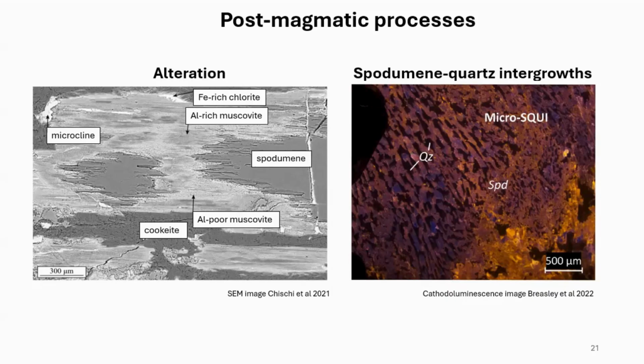It undergoes this calcination. To get the lithium out of solution is another story. That's lithium hydroxide, carbonate, all that stuff. But just to get the lithium in a leachable form, you have to heat it up. Guess what happens when you heat this up to 1,000? Muscovites melt first. So the muscovites melt and then provide a glass coating on top of the spodumene grains, which drastically decreases your recovery rates. Because you just coated all of the ore minerals. Now you're not recovering.